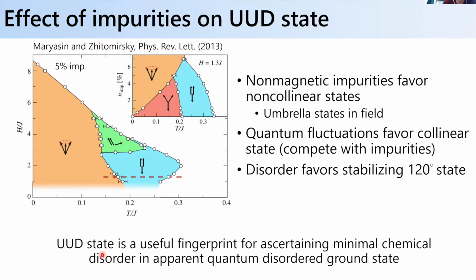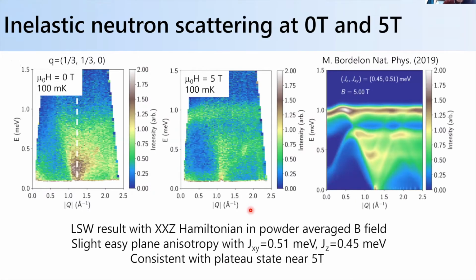And so that makes the up-up-down state a useful fingerprint in our mind for saying that the presence of chemical disorder in generating the disordered ground state under zero field can be ruled out to reasonably good confidence, because the up-up-down state is still allowed to be stabilized, and it should be much more sensitive to the presence of chemical disorder in the system. Okay, so it was a nice additional way to fingerprint the system. The other nice thing we can do is then take the inelastic scattering spectrum.